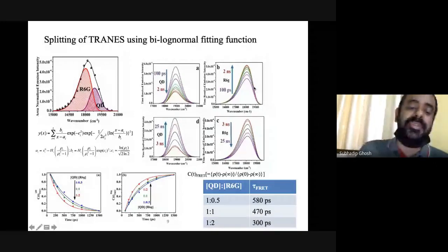Now, as we increase the concentration of rhodamine 6G, the FRET time scale will be faster. This is obvious because when you have a large number of acceptors around the donor, the transfer will be more efficient. We found this at different ratios of quantum dot to rhodamine 6G. This is 1:2, and when it is 1:2, your FRET time scale becomes shortened.